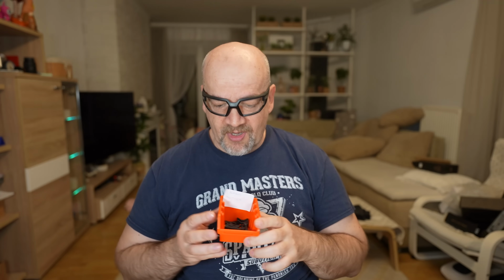Objects are printed ready for mechanical testing, but I will wait at least 3 weeks, so the test objects will absorb some moisture from the air and be closer to that stable state. Now, Elegoo doesn't mention anything about annealing on their website, and I know that in most cases users will not do this annealing process. Additionally, I don't even know what the base material is. In my experience, annealing helps against creep and improves temperature resistance, but for this video, I will test these objects without annealing.